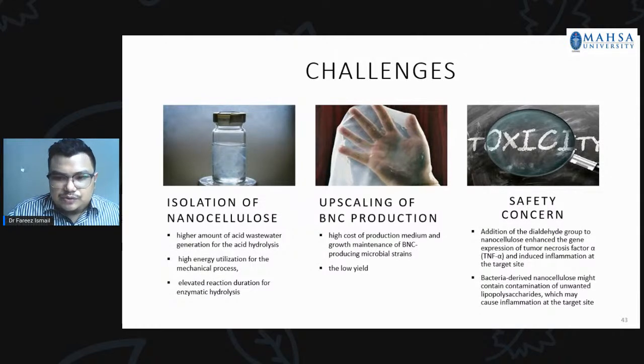For example, a study showed that addition of the dialdehyde groups to the nanocellulose can cause enhanced gene expression of tumor necrosis factor, and also induce inflammation at the target site. Another study shows that the bacteria-derived nanocellulose might contain contamination of unwanted lipopolysaccharide that may cause inflammation at the target site as well. So this is a challenge that we need to solve before we can fully celebrate the usefulness of the cellulose.